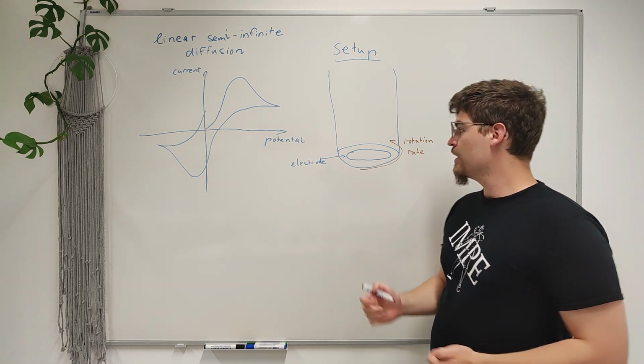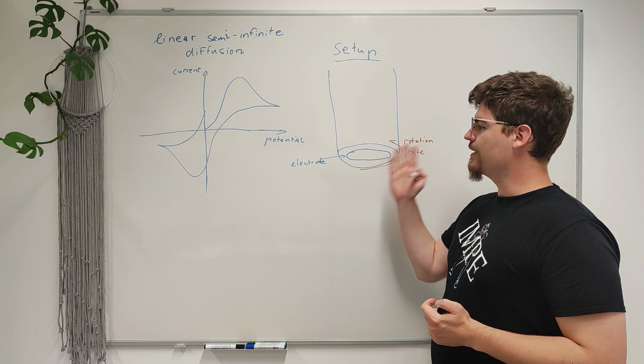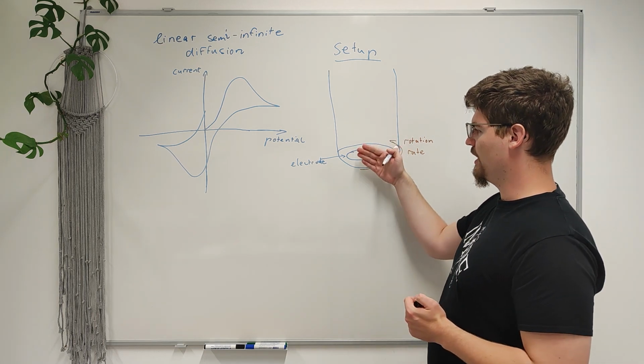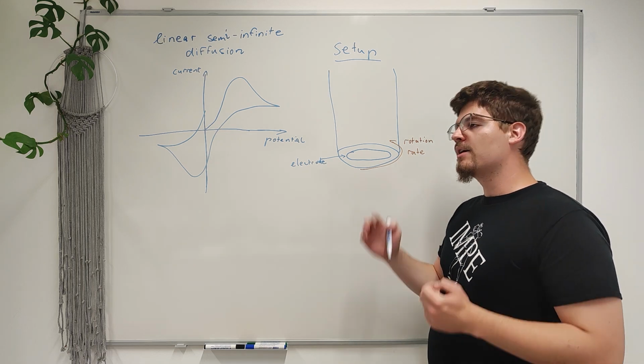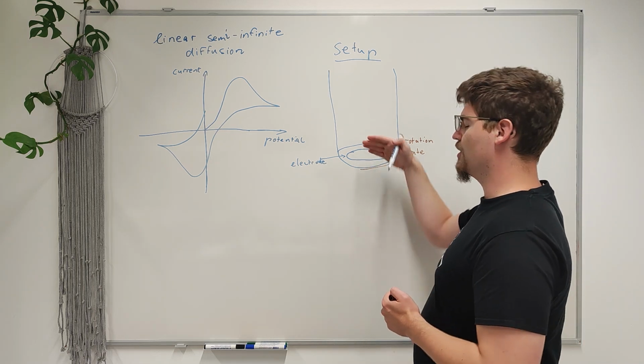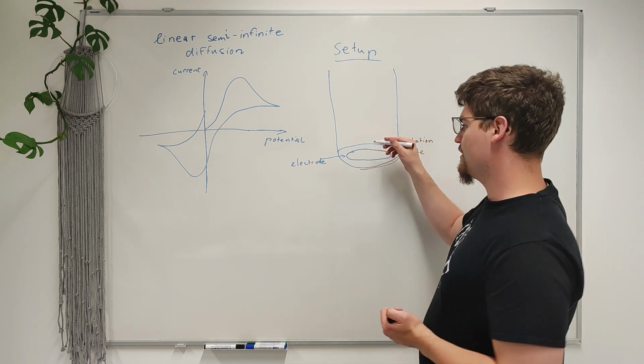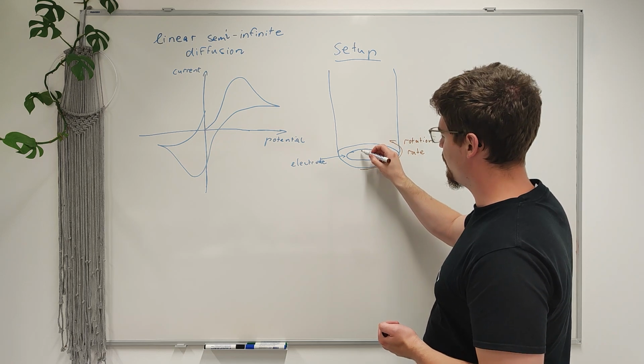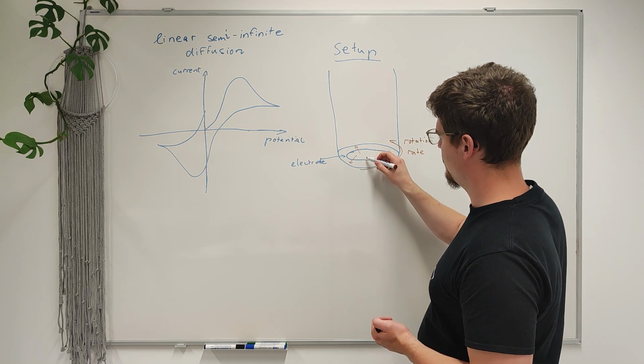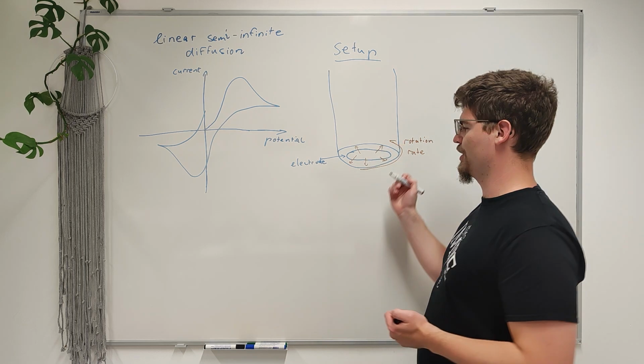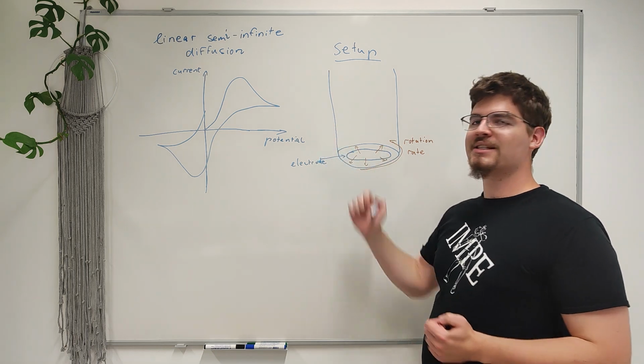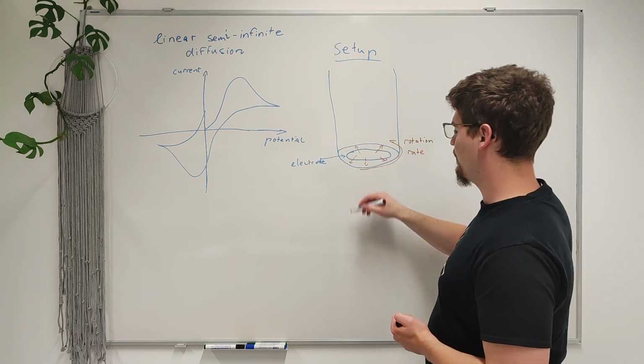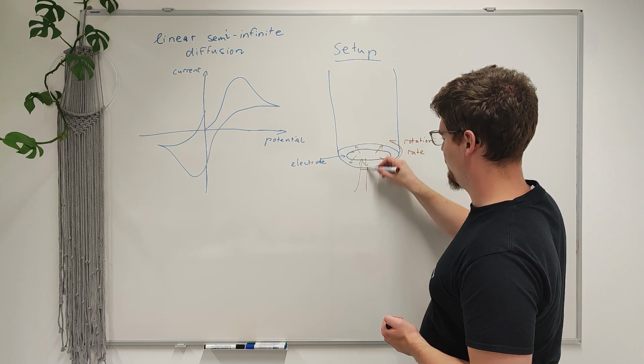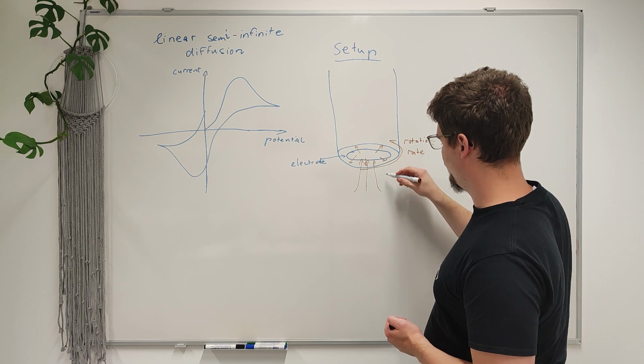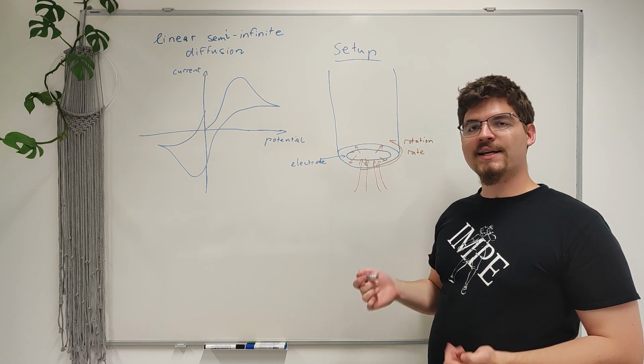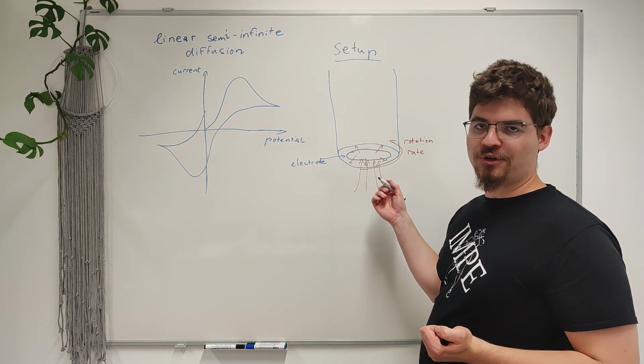Now what does that do? First of all, as we rotate this setup, the fluid that is close to the electrode, and this face of the setup, is sort of adhering to the surface via friction. And what this means is, as it rotates, it experiences a force outward and is essentially flung outwards in a radial direction. And as this fluid is flung outwards, further electrolyte rushes in from the bulk to replenish it. And what this means is we now have the case where we have forced convection.